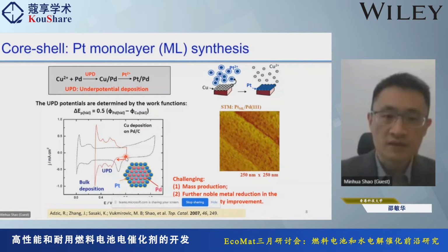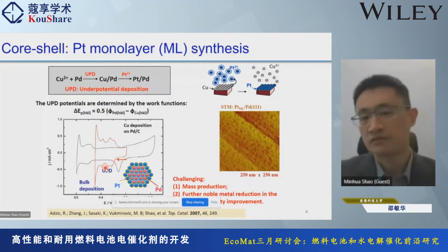And in the copper solution, we can see we start at a high potential and then scan the potential to negative. You can see before it reaches the bulk deposition of copper, this is about 0.37 volt, you can see some of these small peaks. So this current peak is associated with underpotential deposition of copper. So before the bulk deposition of copper, you have one layer of copper deposited on the palladium surface.